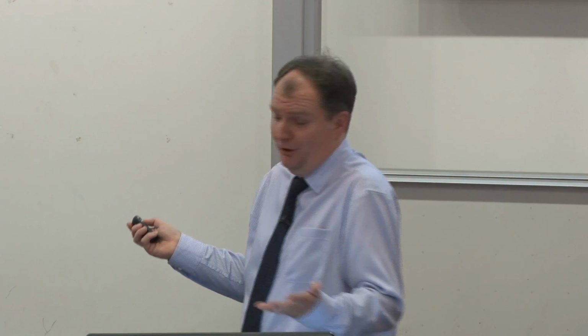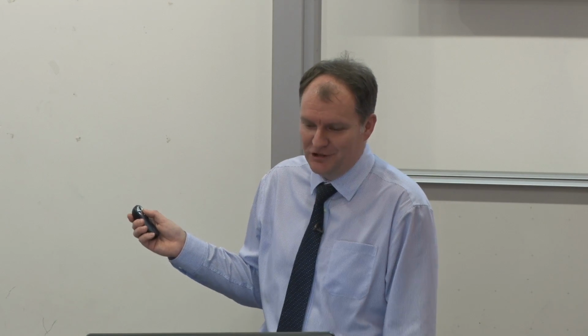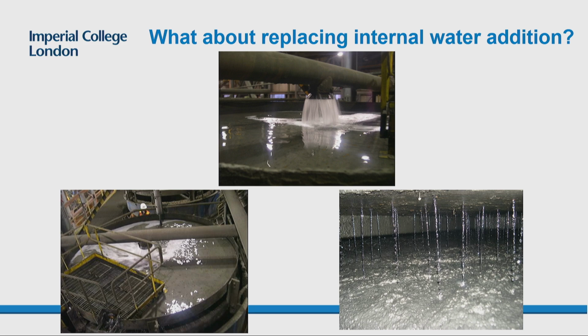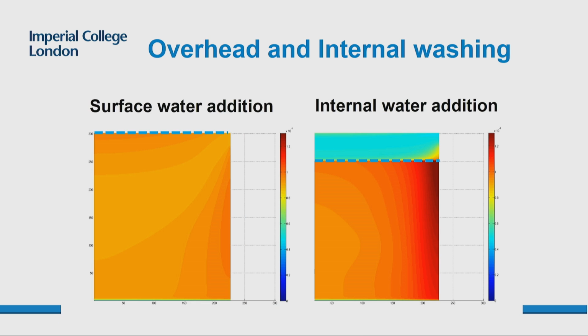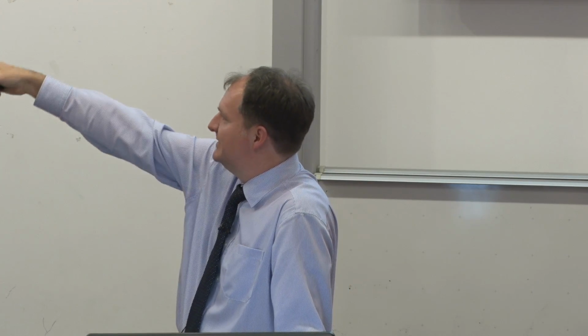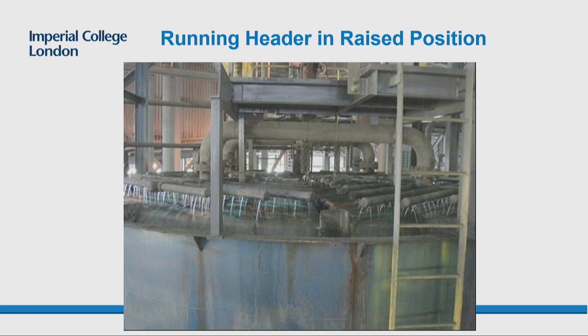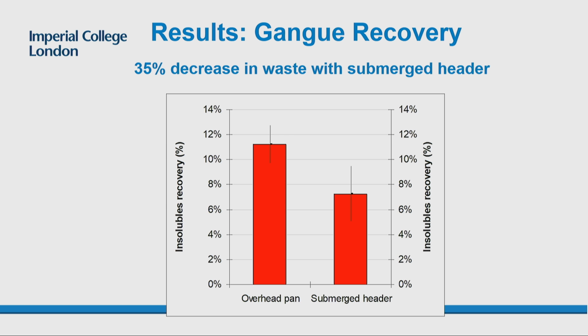Of course, we came back to the original problem, which is whether you should add the wash water addition on the top. We did those simulations as well. And there we found that what they were doing at the moment was the best thing. The froth dries out very rapidly above a water addition point. So you end up with a very dry froth very rapidly above the point at which you're adding water. And so by adding it internally, they're recovering less water and so getting a better performance than if they add it to the surface. And they did some experiments after that where they raised their headers and operated it as though you were doing surface addition, which is not an ideal way to try and replicate it, but at least it gives some idea. And they indeed found that adding it overhead was not as good as adding it internally.